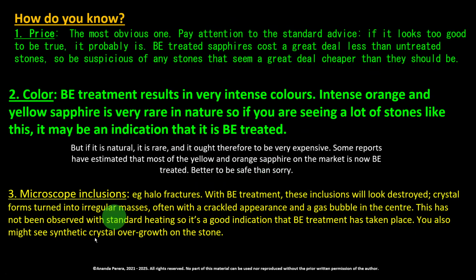Third one, it is microscope inclusions. Example, halo fractures with beryllium treatment. These inclusions will look destroyed. Crystal forms turned into irregular masses, often with a cracked appearance and gas bubble in the center. This has not been observed with standard heating, so it is a good indication that beryllium treatment has taken place. You also might see synthetic crystal overgrowth on the stone.